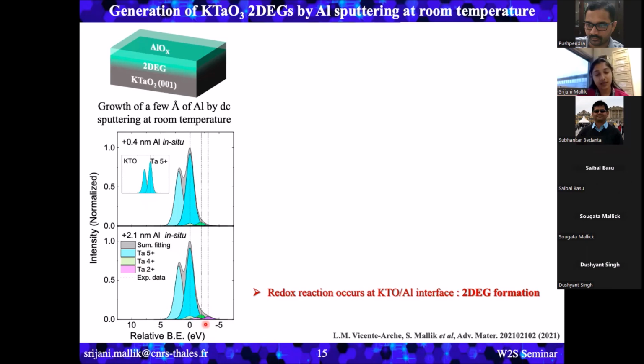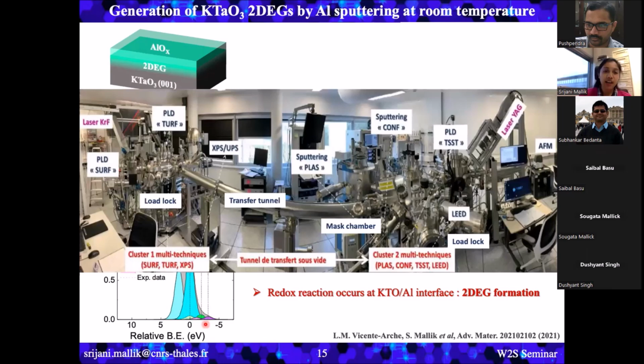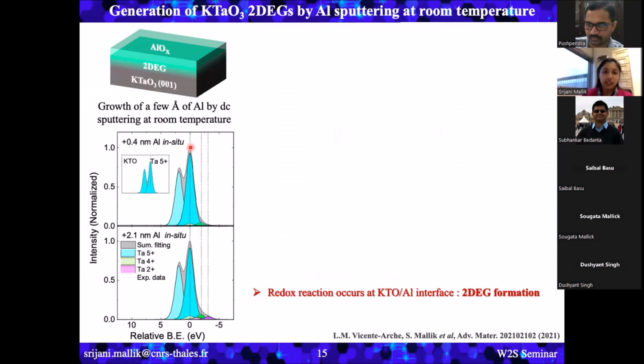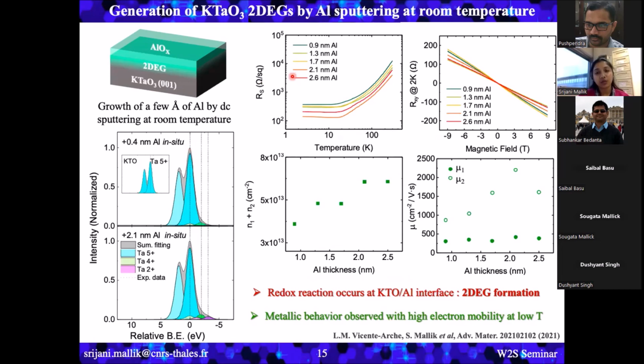All these experiments were done in our deposition system, shown in this photo. You can see we have 3 PLD chambers and 2 sputtering chambers. They are connected in situ with the XPS measurement. We have a MBE chamber and a LEED, everything connected in situ, and we can transfer samples using this transfer tunnel. So we used sputtering to grow the samples, and then we measured in situ using the XPS technique. Then we also studied the transport properties of these samples, and you can see that the samples are very nicely metallic down to low temperature.